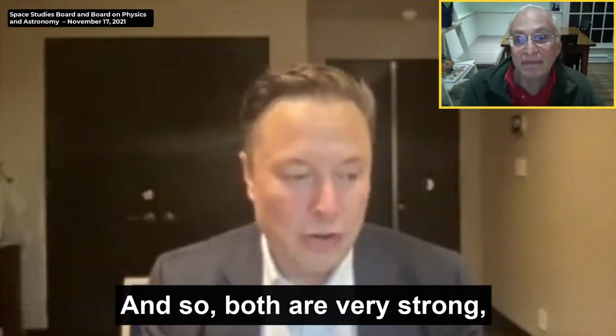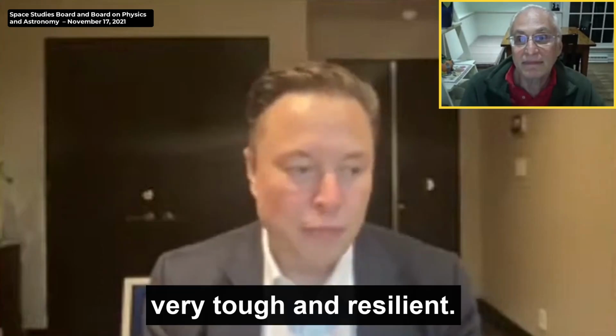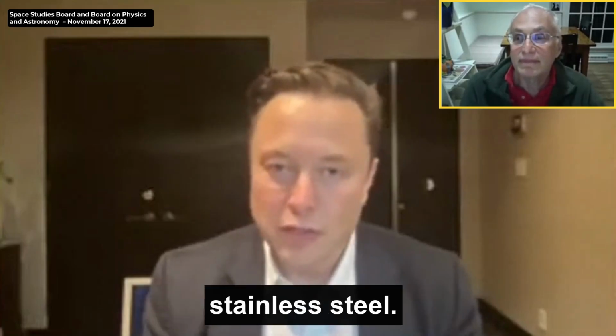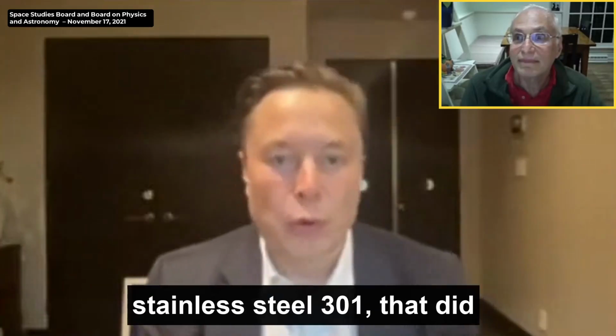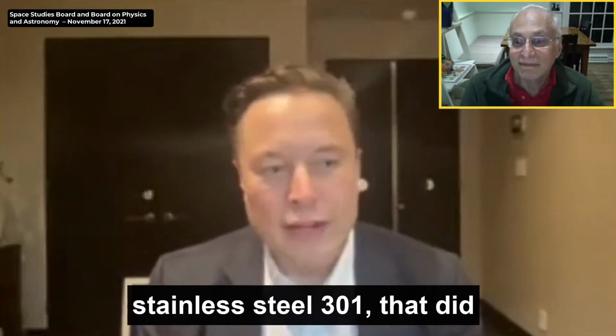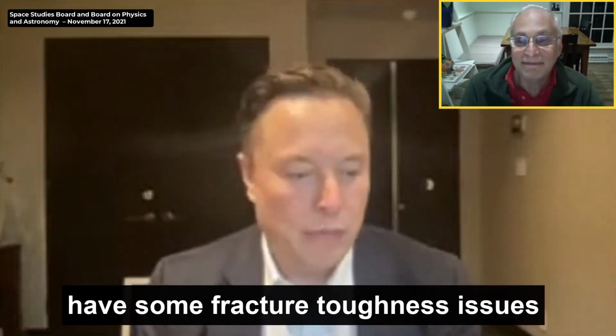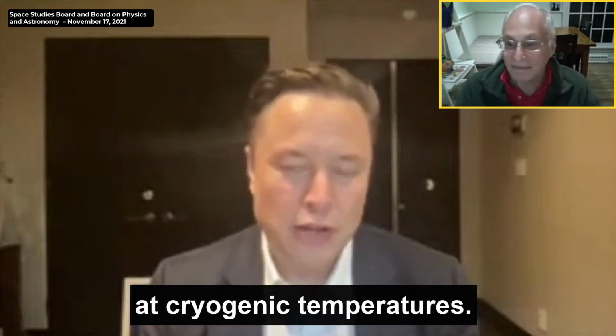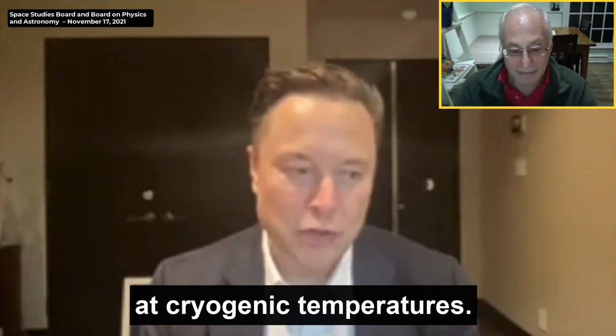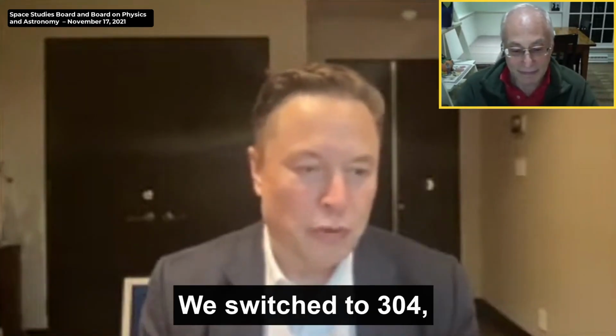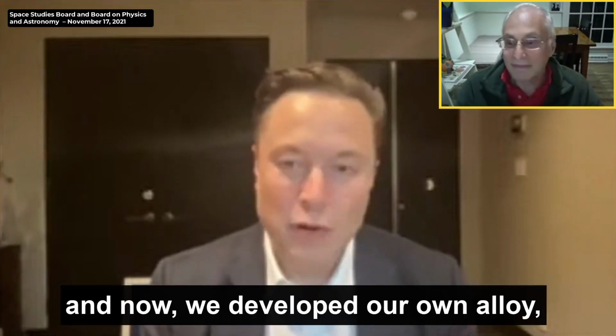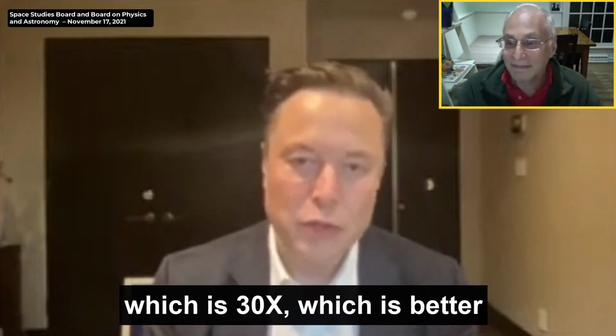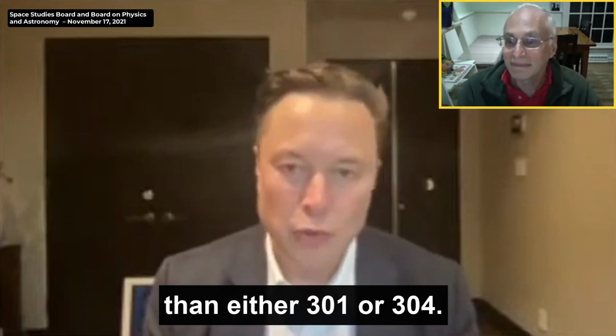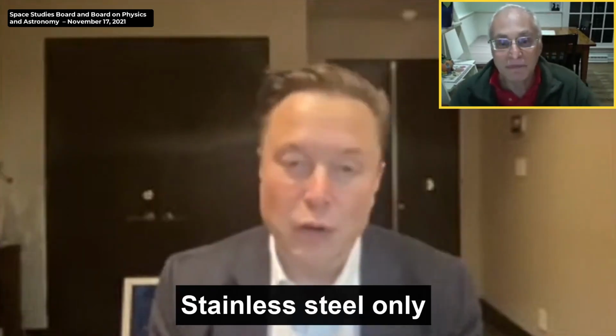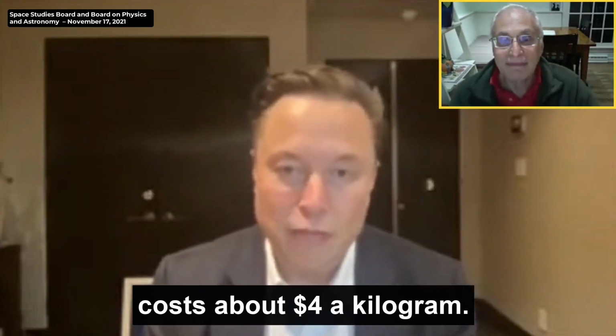So both are very strong, very tough and resilient, also very easy to weld stainless steel. And we started off with stainless steel 301. That did have some fracture toughness issues at cryogenic temperatures. We switched to 304, and now we developed our own alloy, which is 30X, which is better than either 301 or 304. Now, stainless steel only costs about $4 a kilogram.